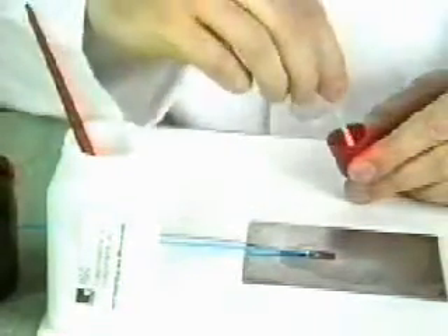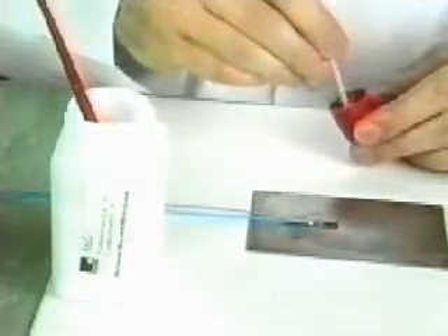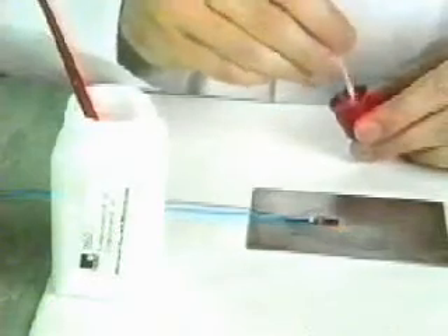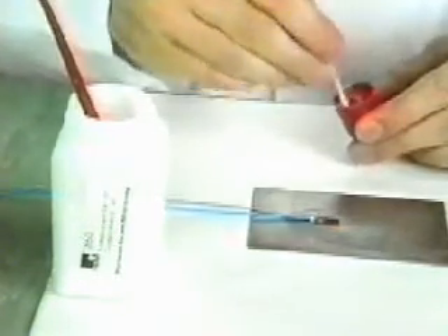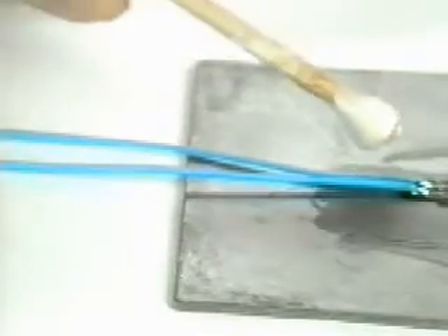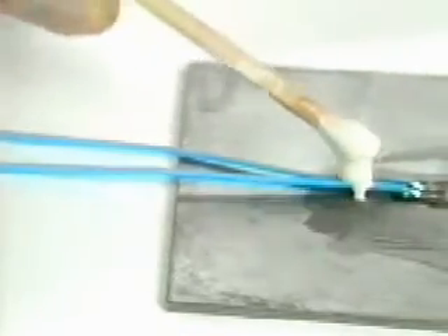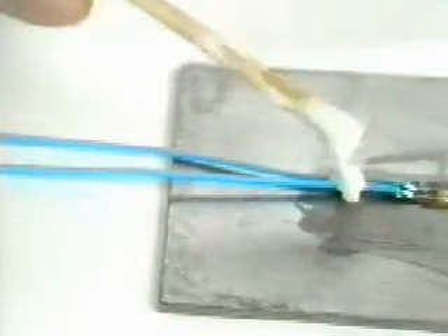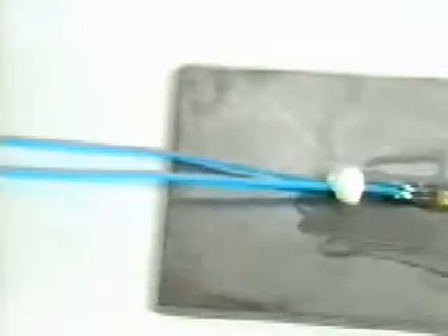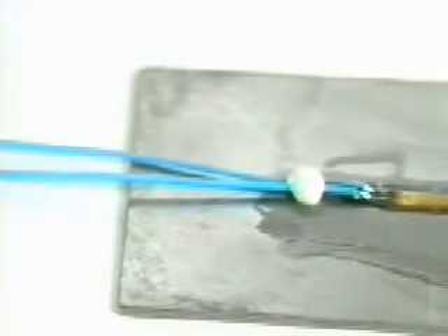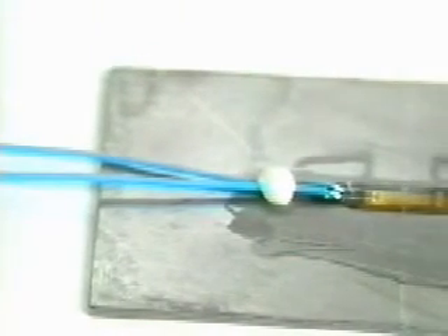A few drops of the liquid component B should be mixed to the powder component A. The adhesive should be mixed so that it's a little more fluid than for strain gauge bonding. This enables it to flow easily between the cores of the lead. Curing takes a few minutes.